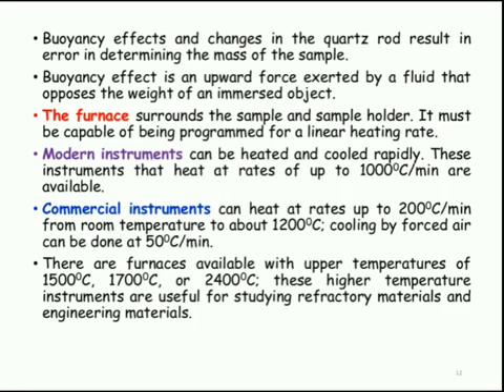Modern instruments can be heated and cooled rapidly. Instruments that heat at rates of up to 1000 degrees Celsius per minute are available. Commercial instruments can heat at rates up to 200 degrees Celsius per minute from room temperature to about 1200 degrees Celsius. Cooling by forced air can be done at 50 degrees Celsius per minute. There are furnaces available with upper temperatures of 1500 degrees Celsius, 1700 degrees Celsius, and also 2400 degrees Celsius. These higher temperature instruments are useful for studying refractory materials and engineering materials.